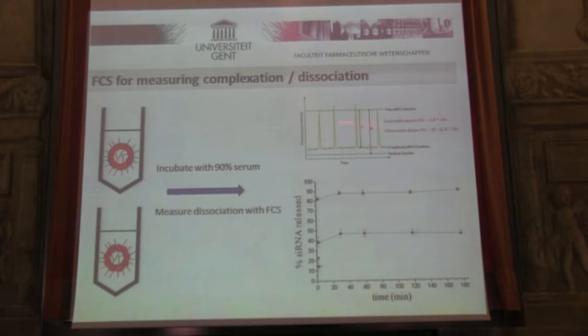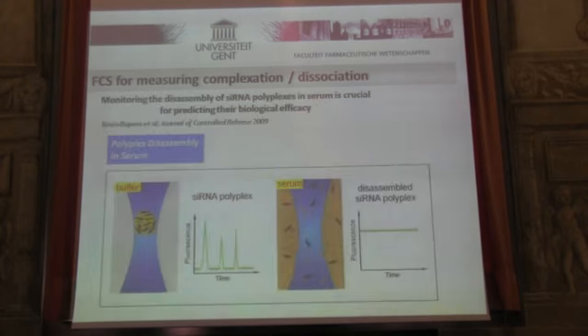And measurements like these tell you something, that this formulation, for example, will never work in vivo. You don't have to go in vivo. Just do the in vitro experiment and you will know beforehand that it will not work. So I think these experiments have value to reduce in vivo experiments. It's not limited to liposomes, so this was a polyplex combination of siRNA with polyplexes. Also here it could be measured that there is a good correlation between the dissociation in serum and the lack of transfection efficiency.